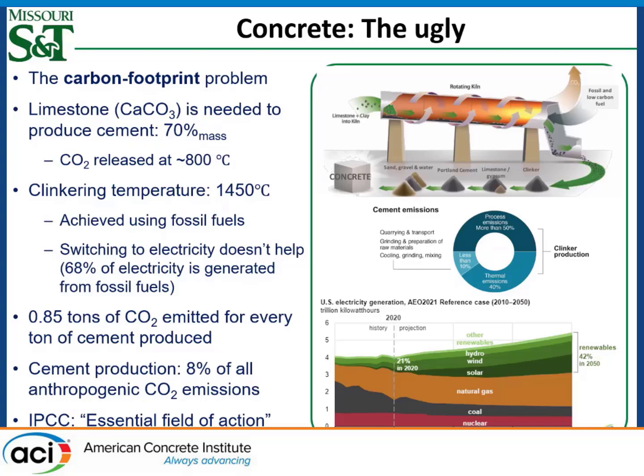And it's really hard for the cement sector to reduce carbon emission because the carbon emission comes from the chemical reaction in the clinker process, the decarbonation of the limestone, and the formation of alite, because you need to burn fossil fuel to heat everything above 1450 degrees to get a lot of alite. Due to restrictive government policy, it's also very expensive to buy carbon credits. So cement manufacturers start to take some action to adopt sustainable manufacturing processes.